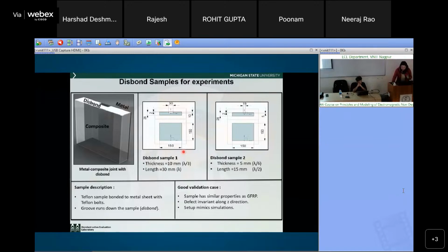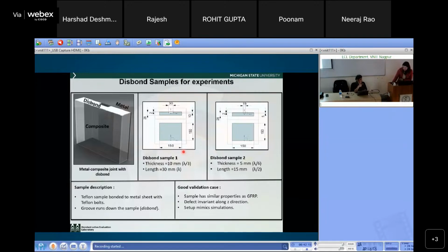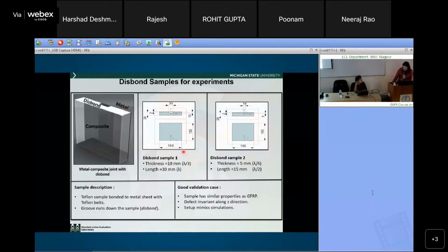She's telling far field, 7 to 10 gigahertz. So if it's far field, then there is diffraction. Even I showed the GFRP with 3 holes, and we could detect the biggest hole in the far field. You will not detect the smaller holes because of the diffraction limit in imaging. If it's less than lambda by 2, you're not going to detect it. That's the holes. But reflected fields by the foil are detectable. That is why she was not able to detect this Teflon tape. That also depends on the size of that. So what was the size? Can you tell us?